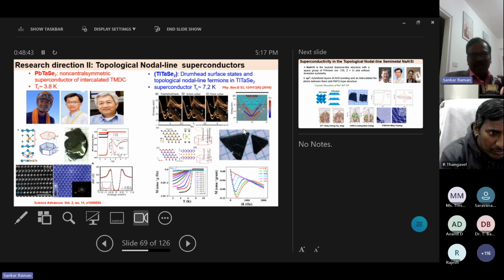And we also did an excellent STM. We found the superconducting gap too. It belongs to s-wave superconductivity. With the same method I tried thallium, because you people know 3.8 Kelvin is good for STM. ARPES takes a long time, more than six months of work.